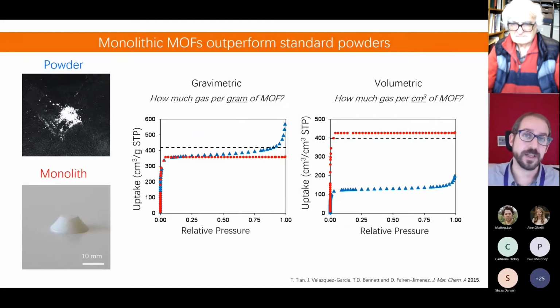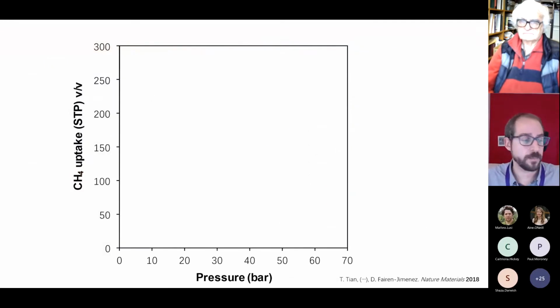This is amazing because now we can really use the data that we are getting from the molecular simulations, because now we are going to have a density which is real. The density of the monolith is very similar to the single crystal density, whereas in the powder, you have this density plus a lot of void space between the particles, and therefore really a fraction of the original density of the single crystal.